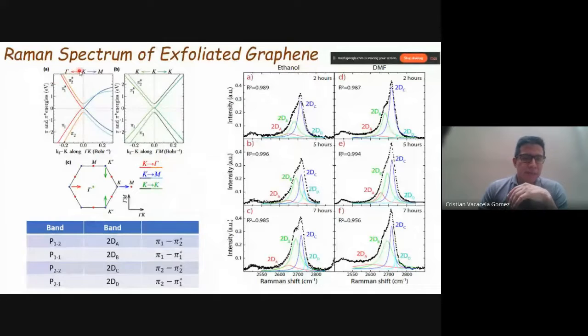If we take the high symmetry path, for example, gamma, kappa, M, or kappa, we can see this is the famous Dirac cone. Of course, the Dirac cone is not well observed in bilayer graphene. However, I use this image to show how the bands are. For example, here in the valence bands and the conduction bands, we have pi 1, pi 2, pi 1 star, pi 2 star, and similarly for figure B. From this picture, you can see the different transitions: pi 1 to pi 2 star, pi 1 to pi 1 star, pi 2 to pi 2 star, pi 2 to pi 1 star. So you can connect them, and from this we can analyze why in this 2D band region the few-layer graphene or bilayer graphene dispersions can be fitted by using 4 Lorentzian functions. That is important here.